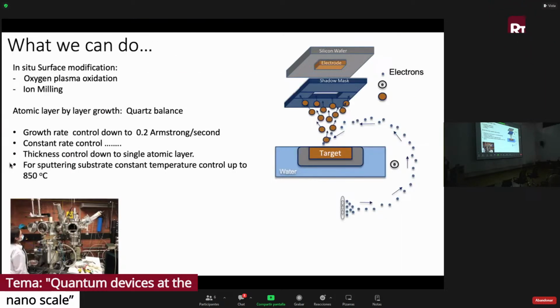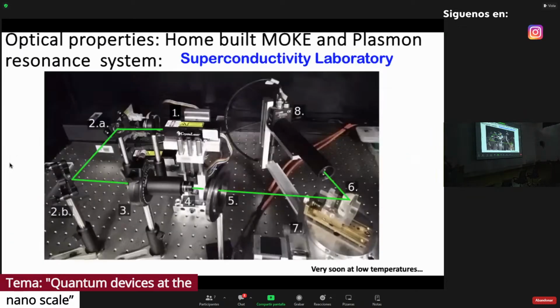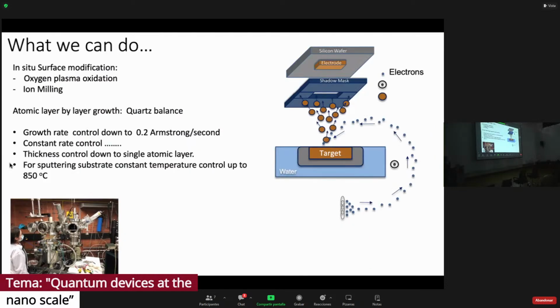What we can do: we have an oxygen plasma oxidation system, ion milling for fabrication, and atomic layer by layer growth using a quartz balance. We can grow at a rate as low as 0.2 angstroms per second. This extremely low growth rate allows us to make extremely uniform and extremely thin structures of different materials. For the sputtering system, on the other hand, we can control the growth with temperatures up to 850 degrees Celsius.